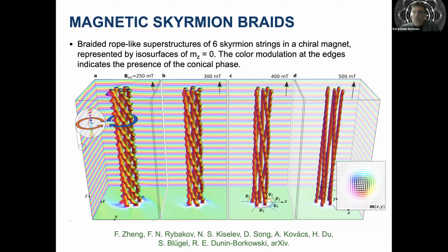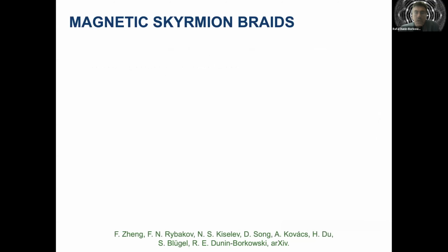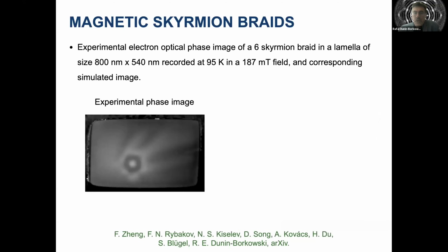However, if in the electron microscope, we again look at a very carefully machined lamella, in this case, a lamella which is 800 by 540 nanometers in size, imaged at low temperature in the presence of an applied field. And if initially 6 skyrmion strings are nucleated in this little iron germanium lamella, then they assemble to form a very curious structure which displays a magnetic phase profile, which is shown in the image on this slide.